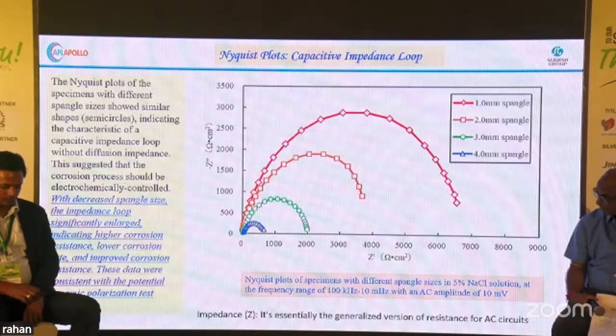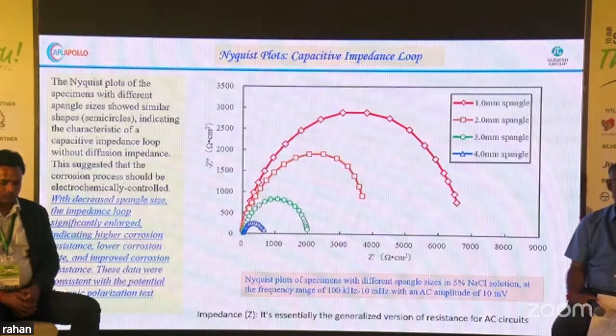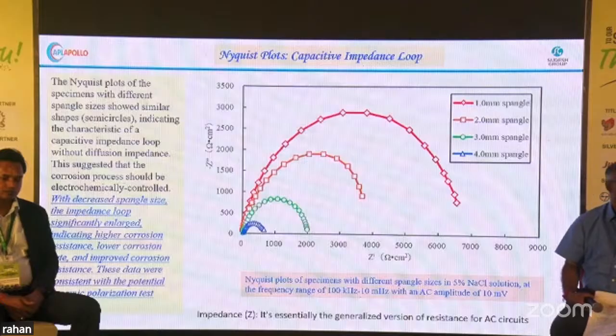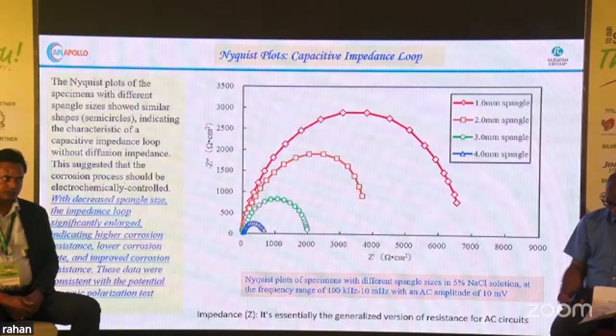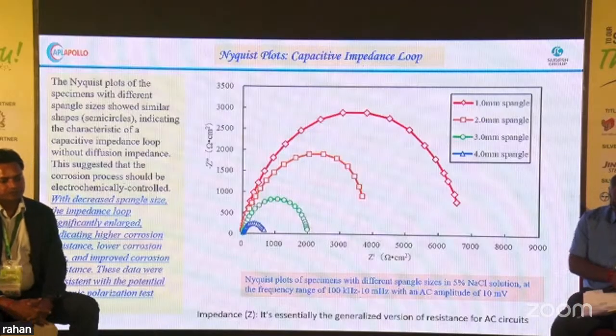By this capacitance impedance loop also, we can see that impedance is basically the combination of reactance and resistance to the AC current. As we know, this corrosion process is electrochemical in nature. So when we are increasing or decreasing the spangle size, there are changes in this loop. By decreasing the spangle size, for the bigger one, the red color, 1 mm spangle, the impedance loop is very, very large.